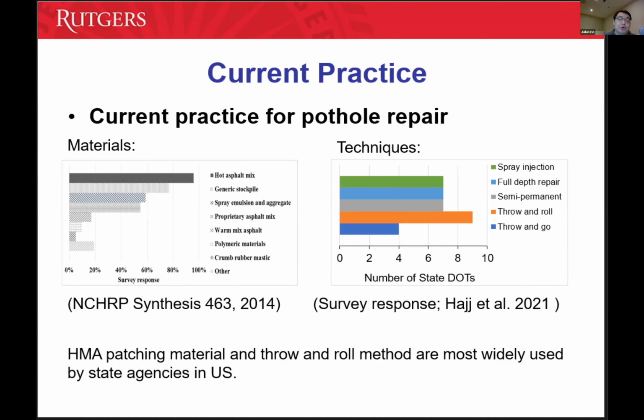And from the method's point of view, you can see here we have spray injection, which is something I just mentioned. You spray the emulsion with some small aggregate together. Full depth repair is more like, if you have multiple potholes, you repair them like normal construction. You bring the vibratory compactor and some large machines, which is pretty costly. The semi-permanent, throw-and-go and throw-and-roll are more like quick repairs. The difference is, throw-and-go is you just dump in some material and then just go without any compaction. In this case, it's usually for emergency repair.